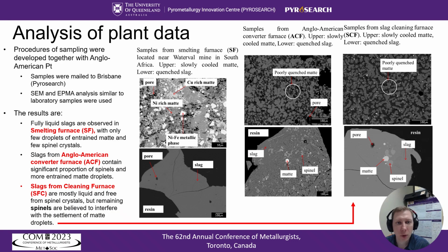The next important step in the project was the analysis of the plant samples. Together with Anglo-American Platinum, we developed the protocol for sampling. The samples were delivered to Brisbane, and we used the SEM to study the microstructure and electron-probe to measure the compositions of phases. The most important were the observations for slags.